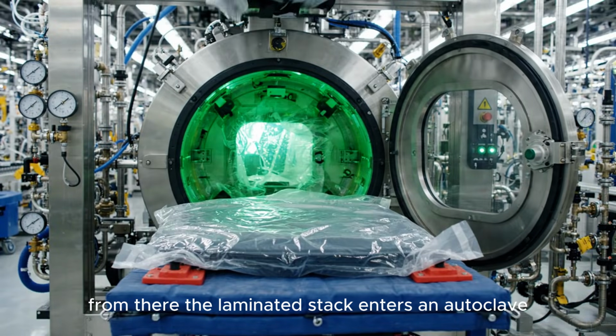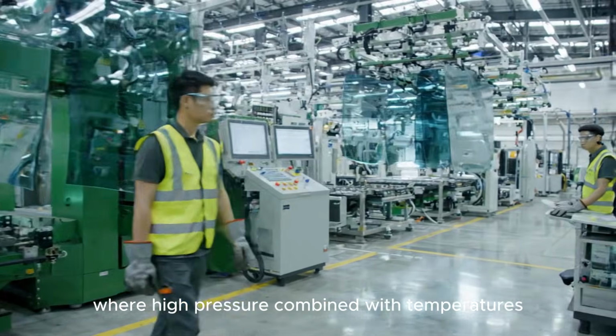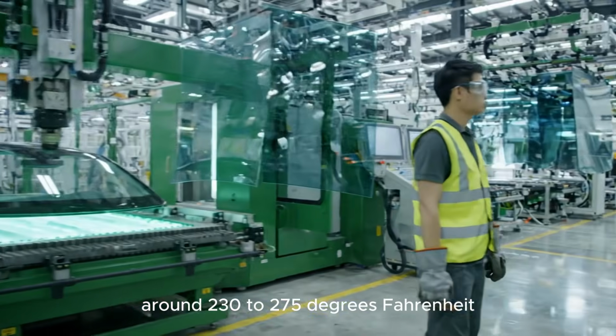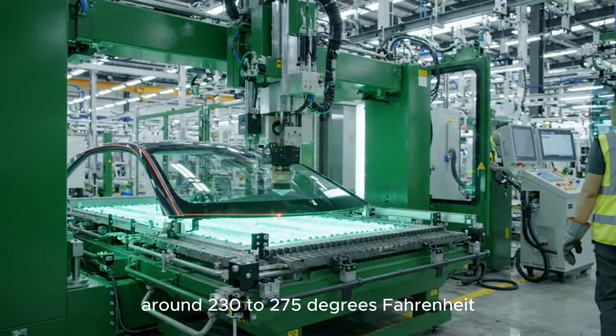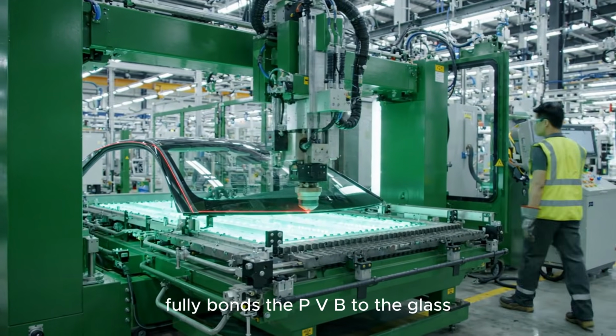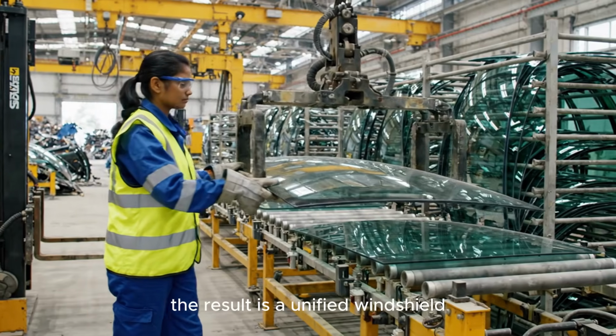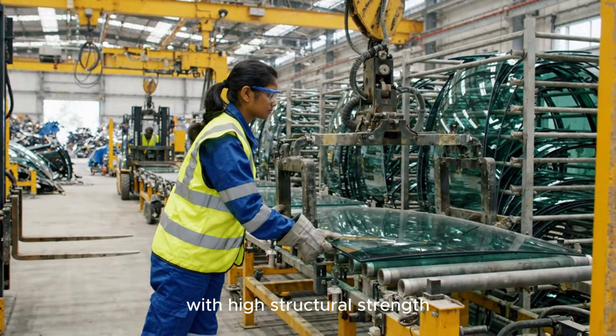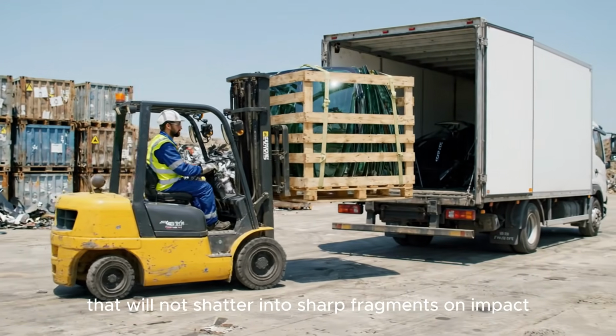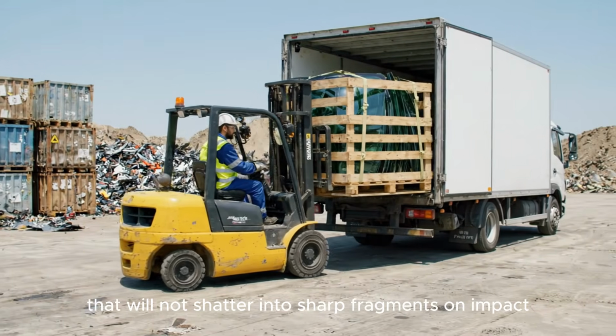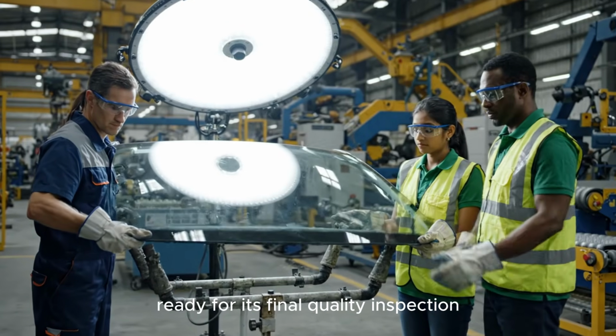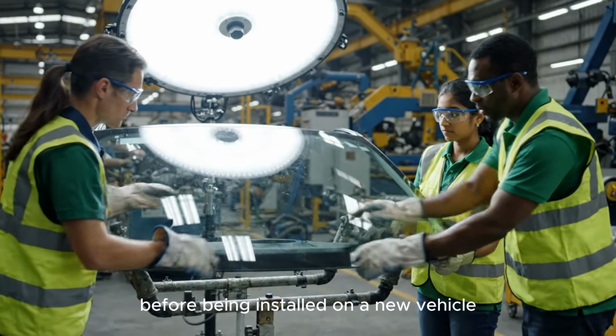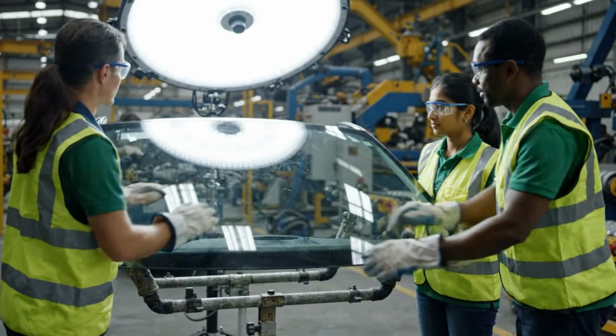From there, the laminated stack enters an autoclave, where high pressure, combined with temperatures around 230 to 275 degrees Fahrenheit, fully bonds the PVB to the glass. The result is a unified windshield with high structural strength that will not shatter into sharp fragments on impact. Ready for its final quality inspection before being installed on a new vehicle.